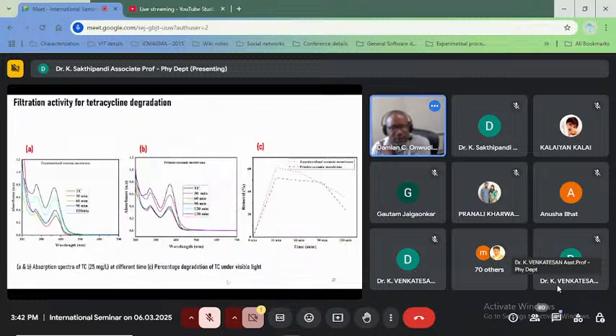Next slide, please. So this is what happened using the dead end cell. The dead end cell allows the water to go in and come out, passing through the ceramic membrane. And so we took aliquots. As the water was coming out from the dead end cell, we took the aliquot and again ran the UV. The figure here also shows that the tetracycline was degrading sequentially as time progressed.